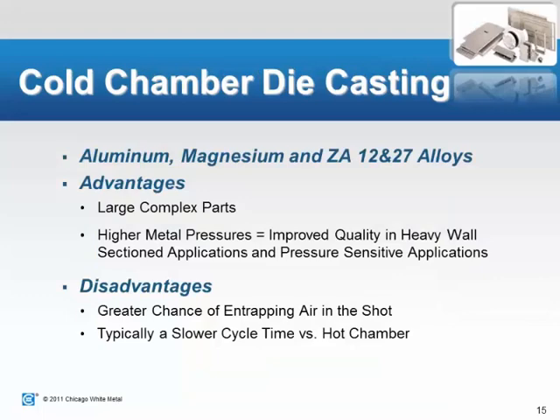Again, cold chamber die casting is for the aluminum, larger magnesium, and the ZA family of alloys that have the higher aluminum content, the 12 and 27% aluminum. Some of the advantages: it allows us to process larger, more complex parts. It allows for higher metal pressures, which gives an improved quality when we have heavier wall section parts, usually in the larger aluminum parts, as well as pressure-sensitive applications.